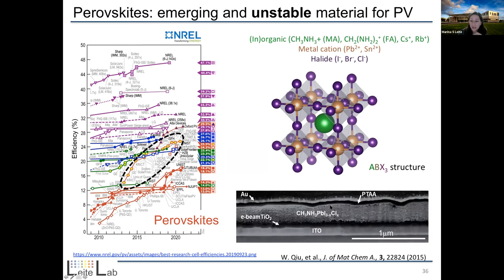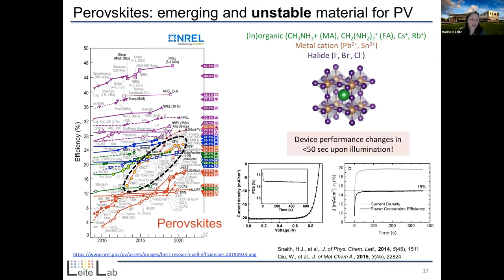So anyway, this is what the solar cells look like. If you look at a cross section here, you can see it's a thin film. It absorbs light extremely well, as well as gallium arsenide, which is fantastic, but it changes. And it changes very quickly. The changes that we see happen on the scale of seconds. What this plot is showing is how the short circuit current and the efficiency, in this case the efficiency, decays as a function of seconds once we illuminate this device. So it's a great material, except that it degrades.